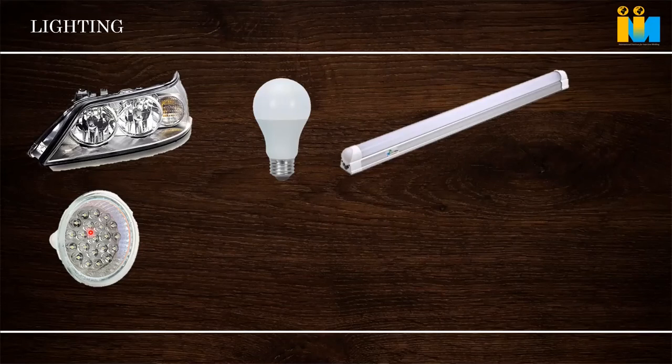This is injection compression. For this lens type of part, some people might have tried with a normal machine, but then blow holes, big holes will come in a 20 mm, 30 mm thick part. It is done by injection compression molding.